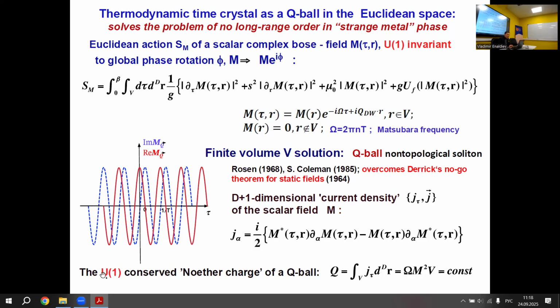And then the U1 symmetry leads to conservation of the so-called Noether charge of a QBall. So if you form such an integral from the time component of this current, you will see that its first derivative over time is strictly zero. What is alpha? The differentiation goes over alpha. So this could be either three-dimensional x, y, z or time. So these are four coordinates.